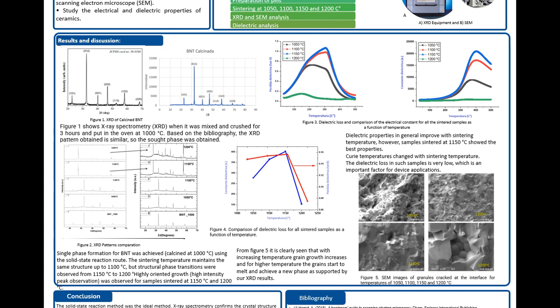Now we can see in figure number 5 that with increasing temperature, grain growth increases, and for higher temperature, the grains start to melt and achieve a new phase, as supported by our XRD results. We can see we have the 1050, 1100, 1150, and the 1200.